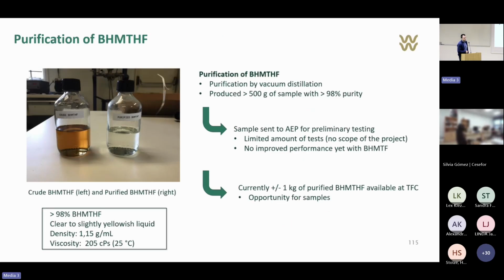So we also looked at the purification of this BHM-THF. We did a vacuum distillation and were able to produce more than 0.5 kilogram of sample with 98% purity. That sample was sent to AEP for preliminary testing. Only a limited amount of tests were done, as David mentioned, because it was not within the scope of the project.